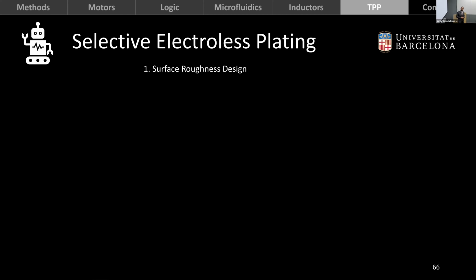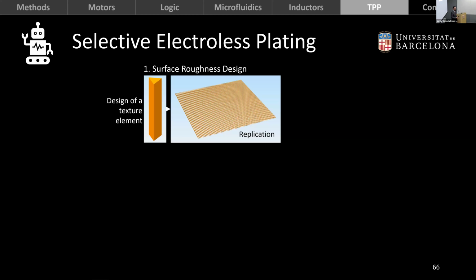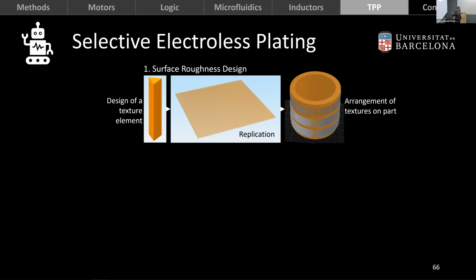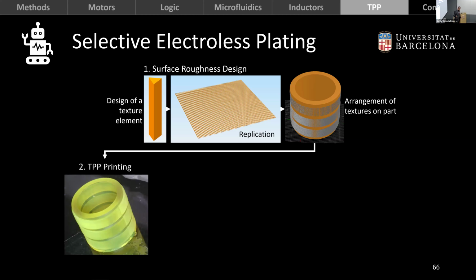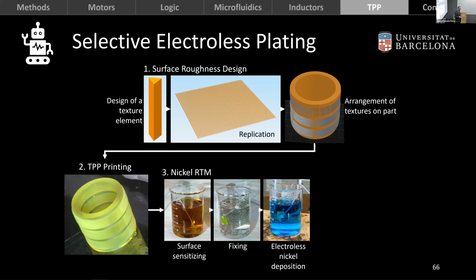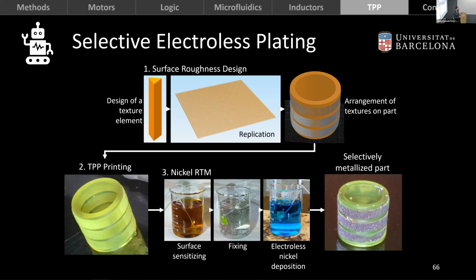So we start with surface roughness design by first designing a surface texture element. We replicate it over a patch, and then we place those patches on the samples that we want to fabricate. Then we can print those samples and put them through the metallization process. In particular, we use nickel room temperature metallization, which consists of a series of sequential baths to end up with a metallized part.